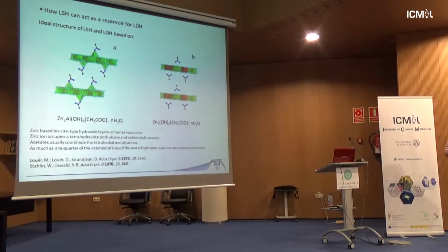The reason behind this is very surprising, because if you compare the LSH to the LDH structure, LSH is in fact an edge-sharing octahedral structure, but you have some octahedral vacancies, and on top of and below these vacancies you have tetrahedra. At the center of the polyhedra, octahedra or tetrahedra, you have the same cation, the same metal, like zinc here. In comparison to LDH, you have